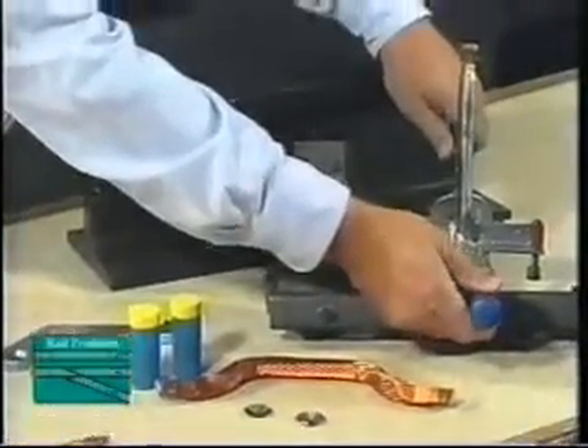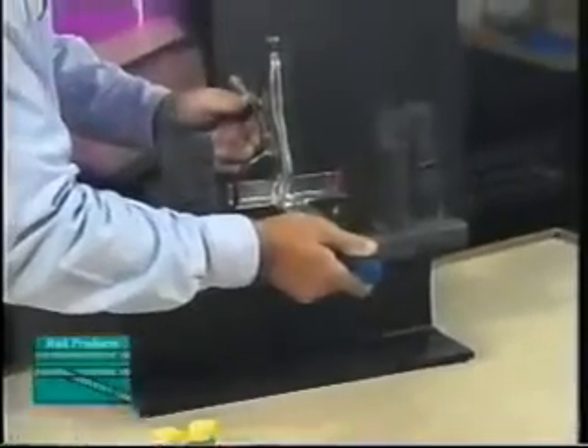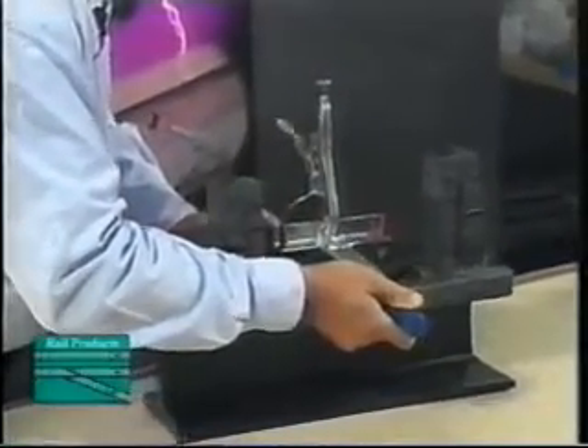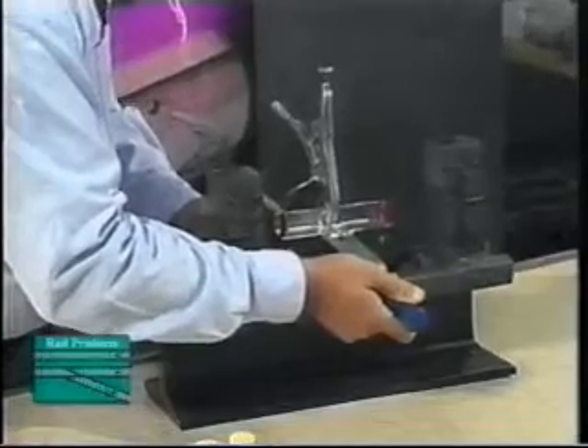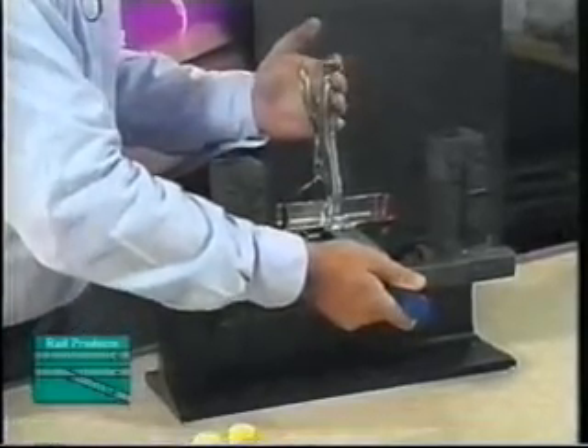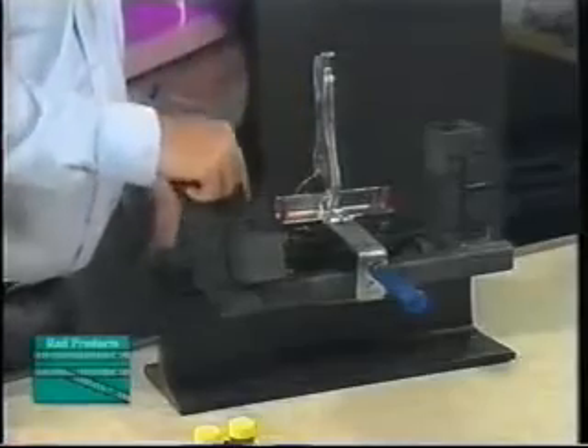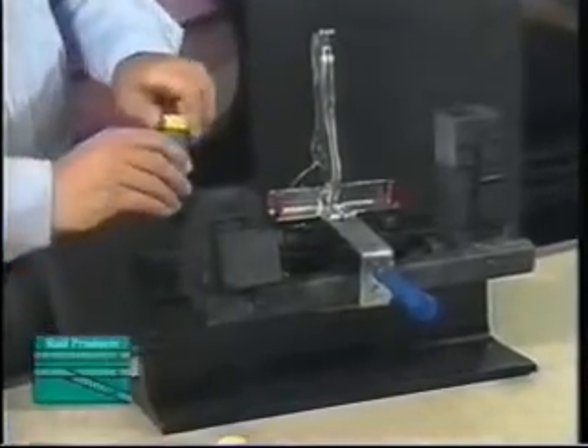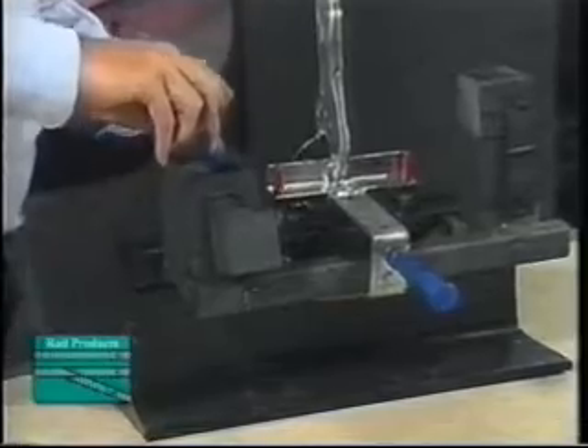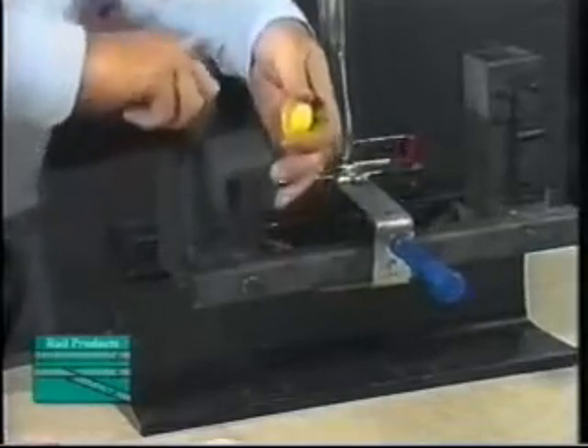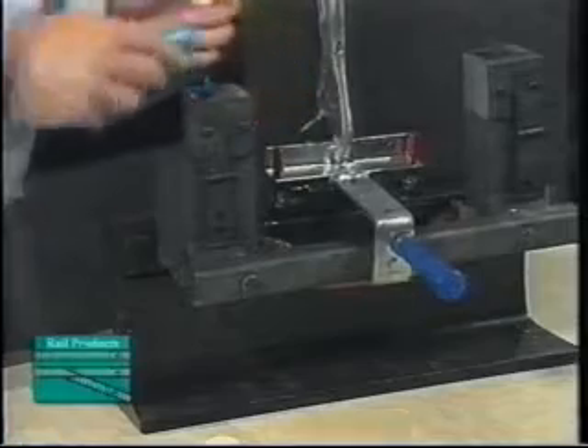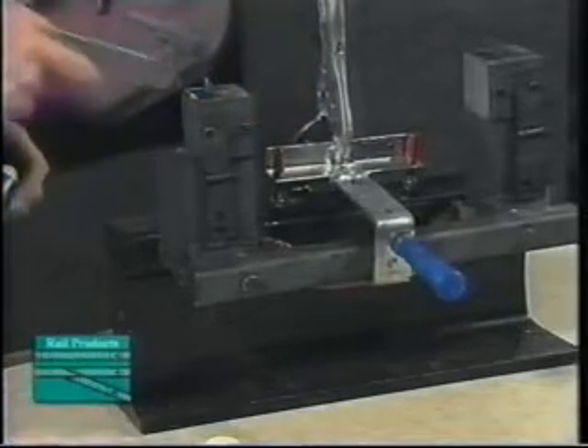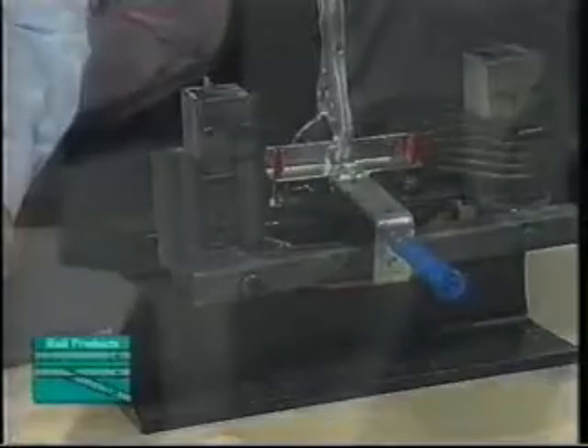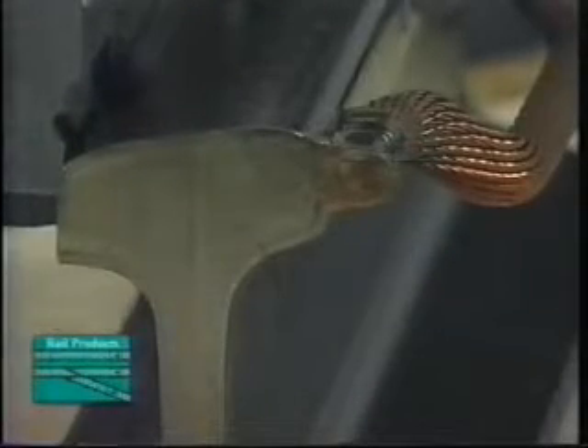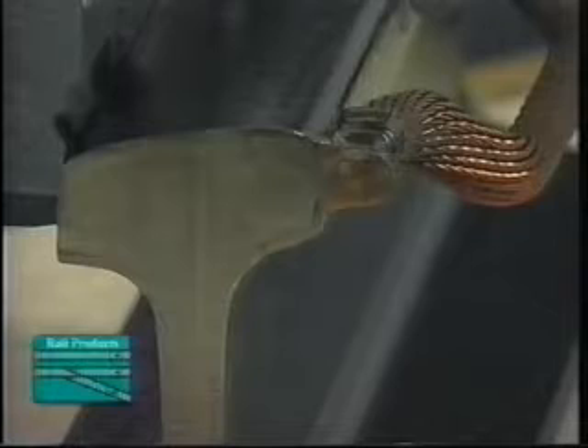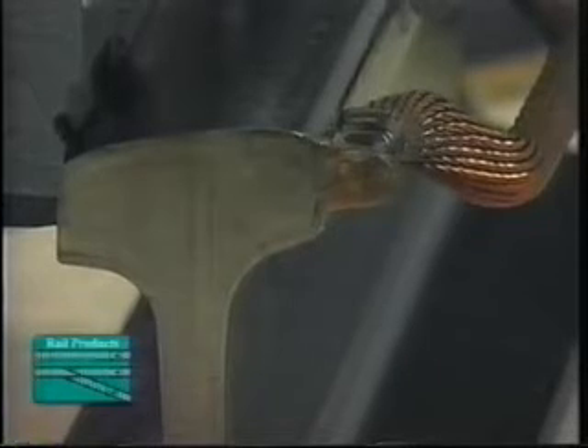Here's how easy it is to weld. Position the welder to the head of the rail. Set the height adjustment screws, then clamp snug to the rail, but not too tight. Slide the disc into the mold. Dump in the proper weld material. Close the lid and ignite the starting material. The weld is complete in a matter of seconds. Here you can see the finished bond connection. We've cross-sectioned the connection to show the quality of the weld.